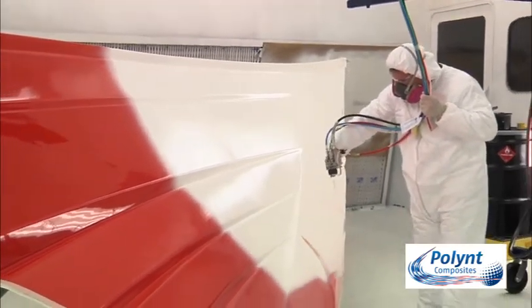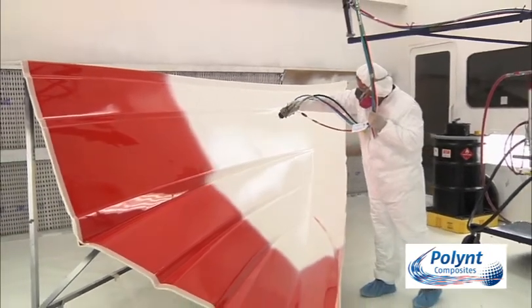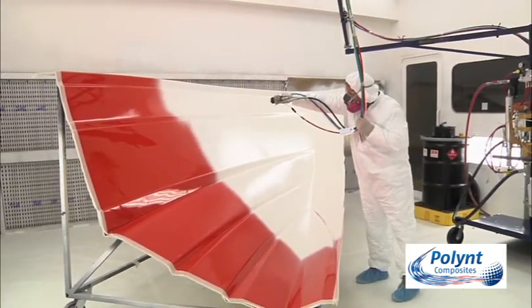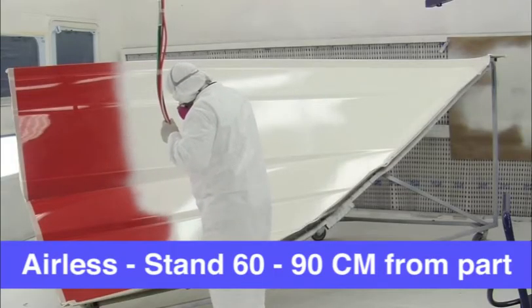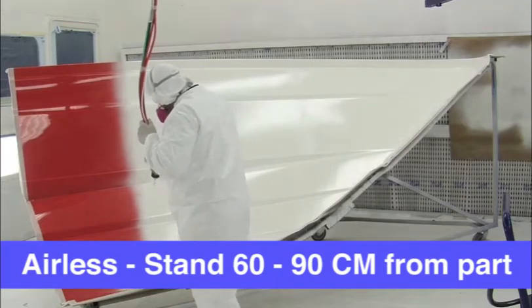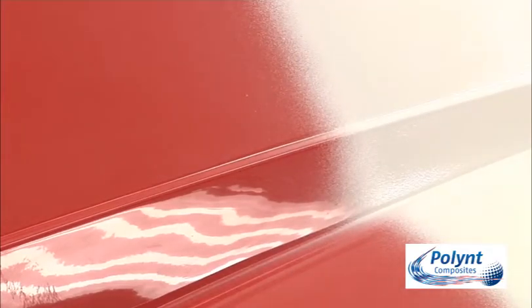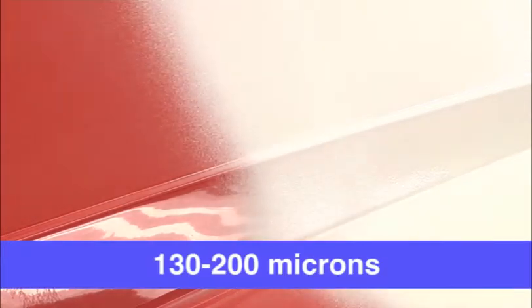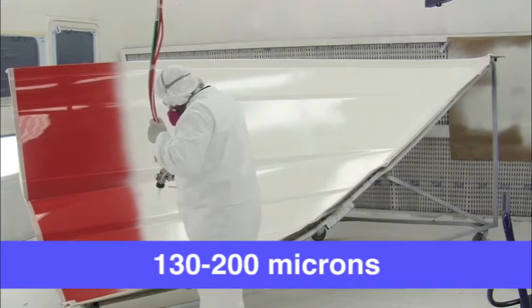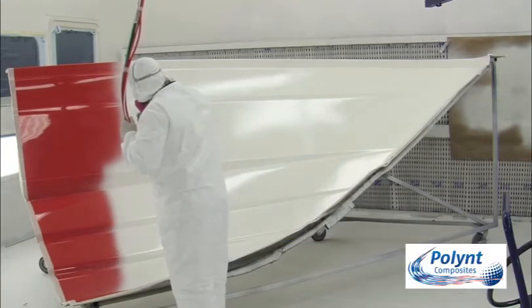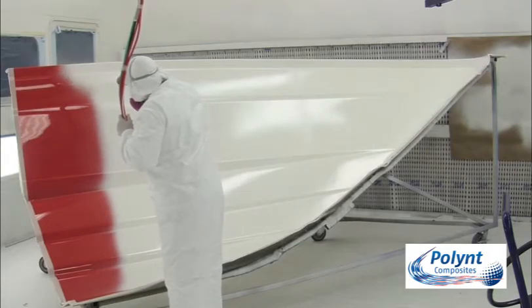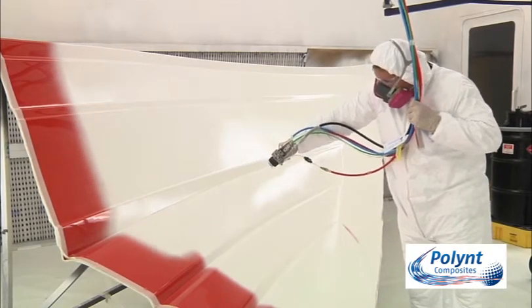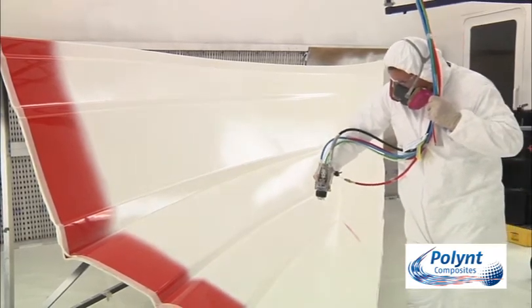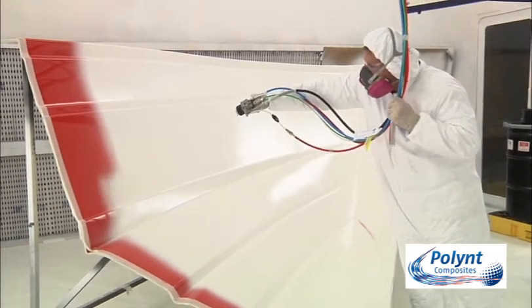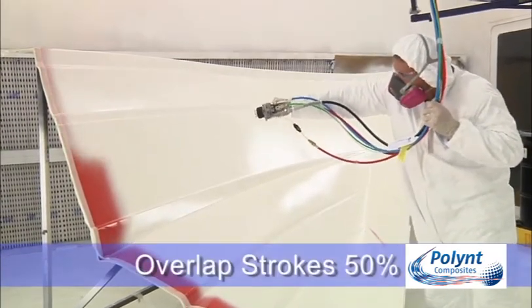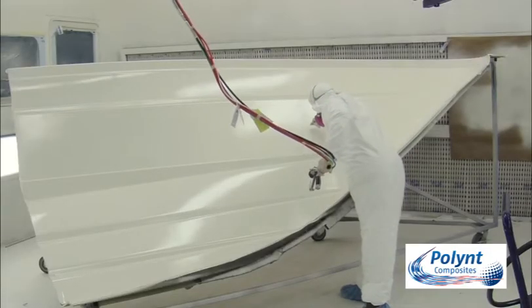Begin spraying nearer the edge in continuous strokes towards the opposite side. Keep the spray gun perpendicular to the mould during each stroke and do not arch the gun whilst spraying. If you're using airless equipment, hold the spray gun 60 to 90 centimetres away from the part. Spray the first pass in a thin, continuous film between 130 to 200 microns, depending on temperature, gel coat viscosity and mould wax. Keep the speed of each stroke even so that a full and continuous wet coat is applied. Stroke length should be about 50 to 100 centimetres. Do not reach for the stroke. Each pass should be parallel to the former, developing a uniform thickness. Overlap strokes 50%.